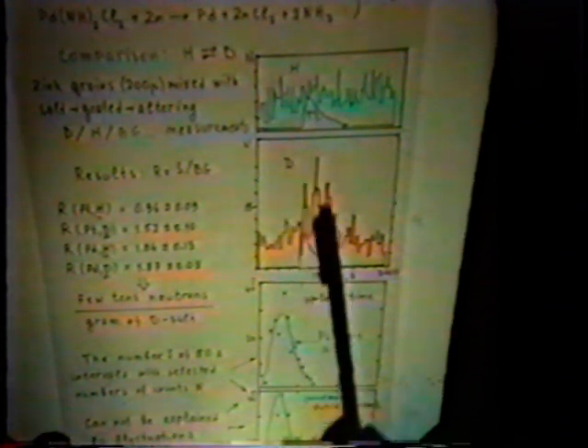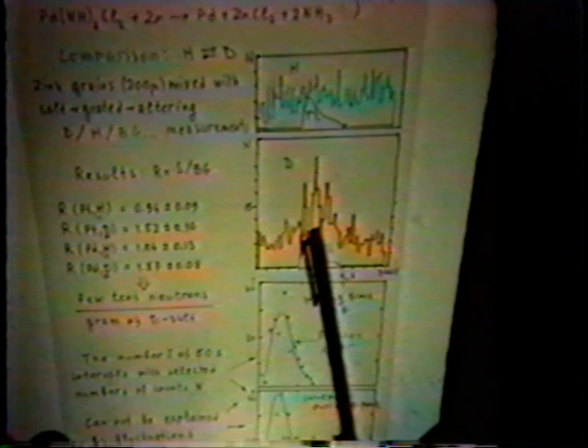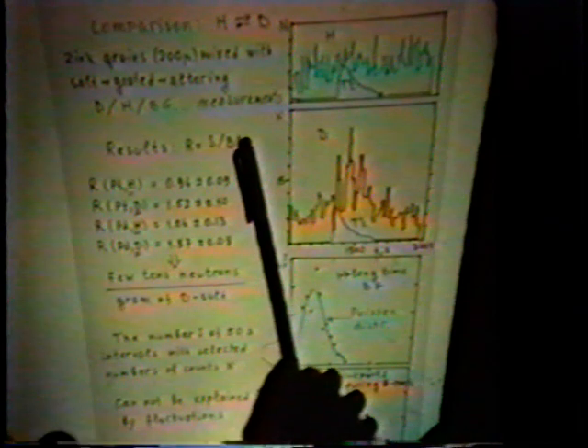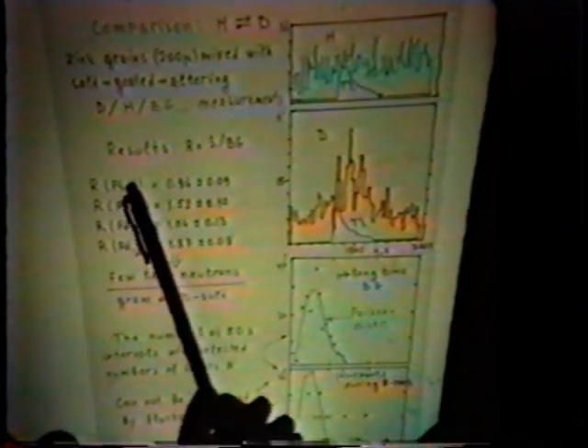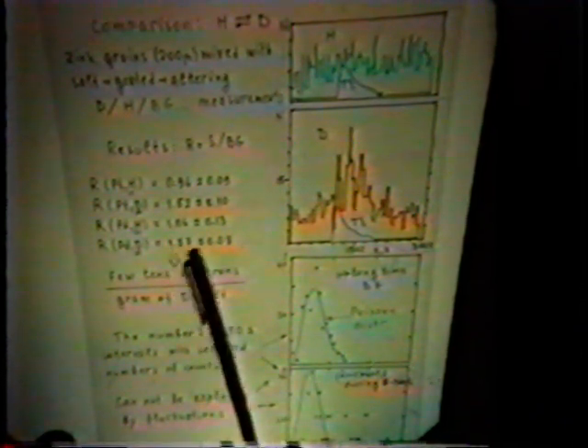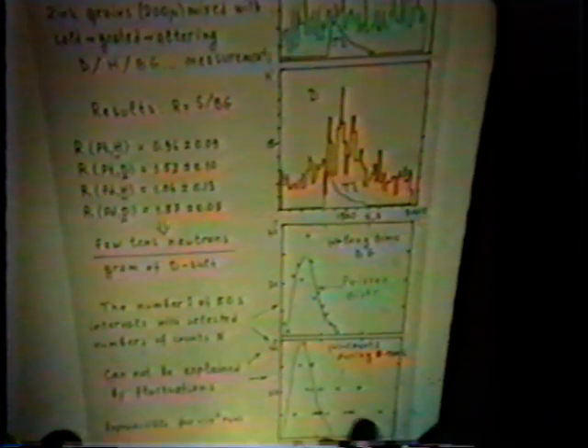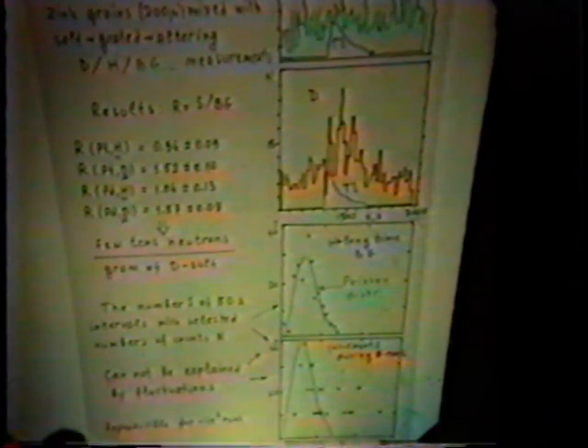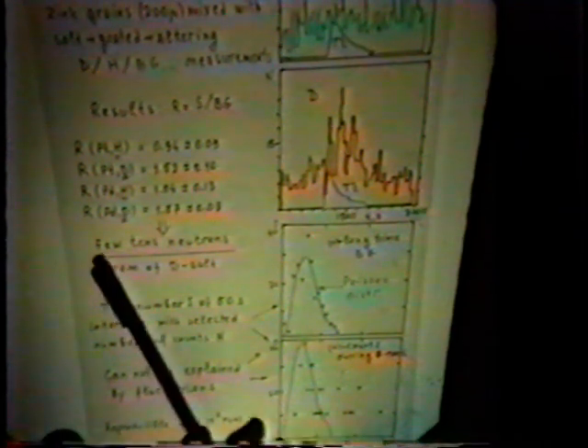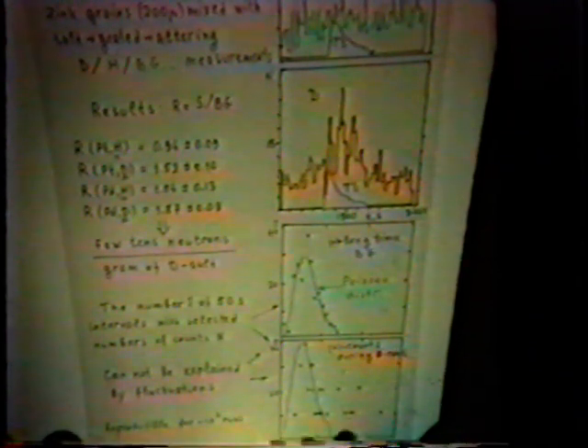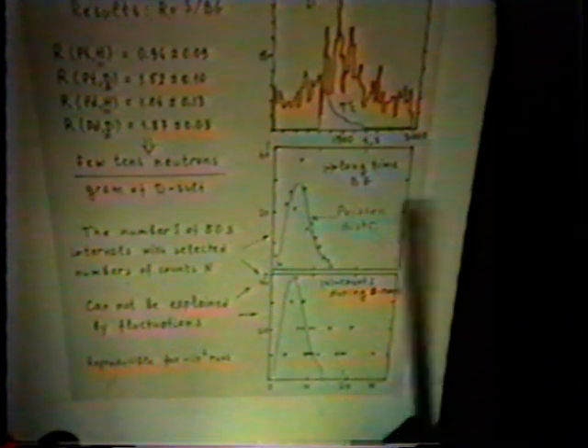And in this case they used deuterium-containing salts, and you can see the difference. The ratio between signal and background level was about 1 for hydrogen salts and 1.55 for deuterium salts. Taking into account the efficiency of neutron registration, this corresponds to a few tens of neutrons per gram of deuterated source. It is important to stress that these results cannot be explained just by fluctuation, as is seen from this figure.